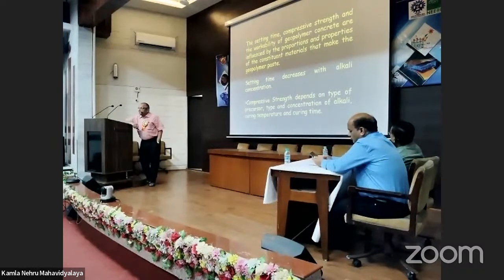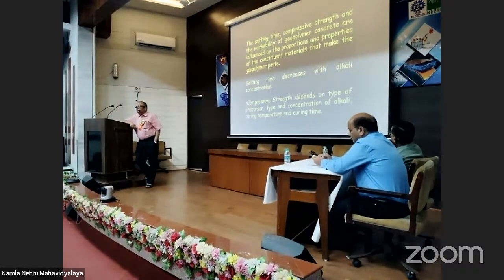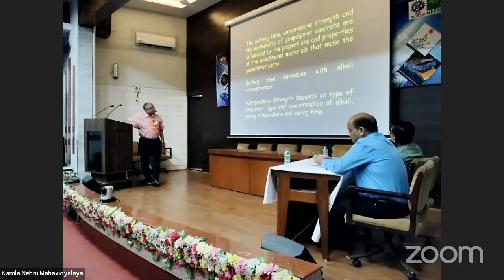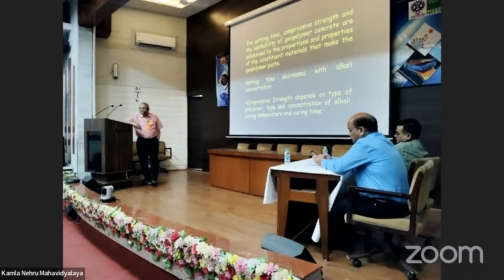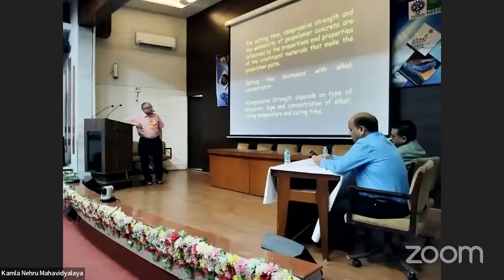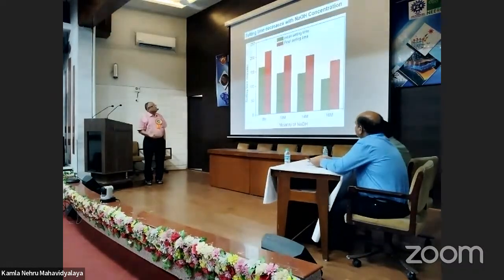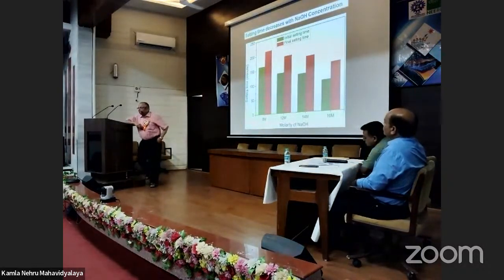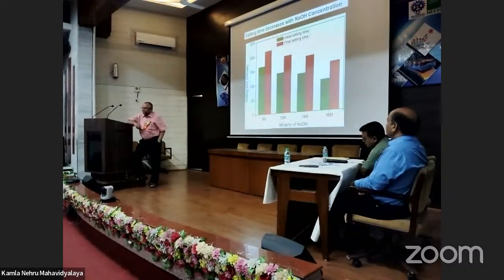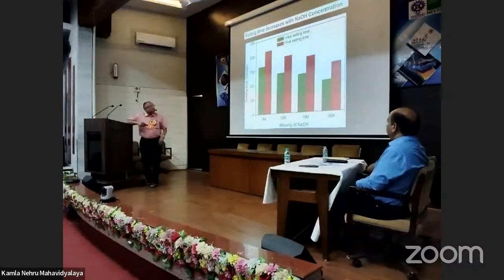Setting time. In the cement industry, setting time and compressive strength are the most important parameters of the properties of the construction material. So setting time decreases with alkali concentration. If you increase the concentration, that is 8 molar sodium hydroxide, 10 molar sodium hydroxide, 12 molar, then the setting time decreases. Compressive strength depends on the type of precursor, whether it is fly ash, slag, etc., and the concentration of alkali, curing temperature, and curing time. Here you see that if you increase the concentration of sodium hydroxide, then the setting time, both initial and final setting time, decreases. In the case of cement, both initial and final setting times are important. And you see that when you increase the concentration of sodium hydroxide, the setting time decreases.